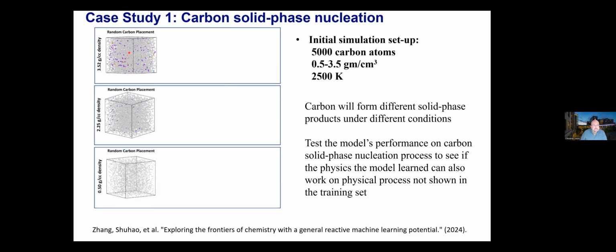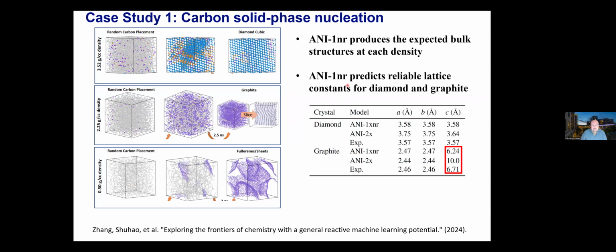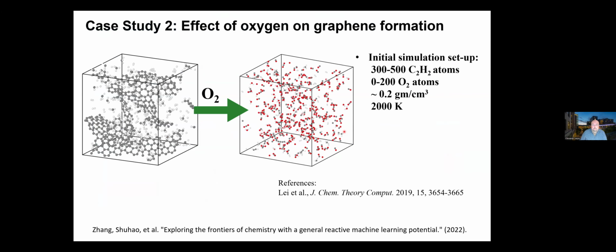So for example, if you run a simulation of high density carbon, medium density, or low density carbon, and do high temperature simulations, you end up with this carbon essentially nucleating into the diamond cubic lattice at high density, into graphite layers at medium density. In a low density regime, you get these fullerene, onion-like structures. You can also describe phonons for the crystal structures and a decent lattice constant for different types of carbon allotropes.